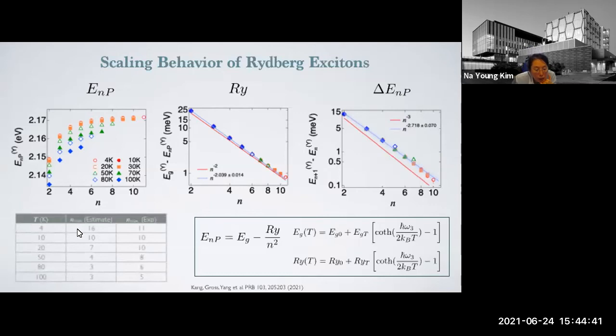Let's take a look at the table. The third column is the maximum n that we could resolve with our detector. At low temperature, we are limited by the spectrometer resolution, and at higher temperature we are not bounded by our spectrometer, it is reduced by thermal effects. One nice result we think is that even above liquid nitrogen temperature, like 80 Kelvin, we can still access n max of about 6.